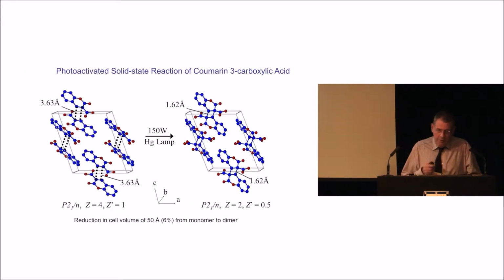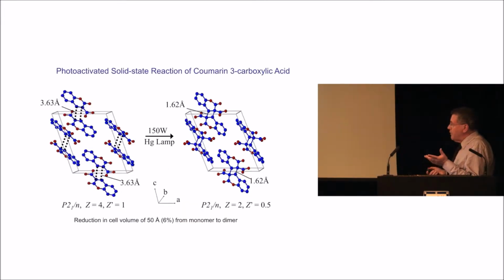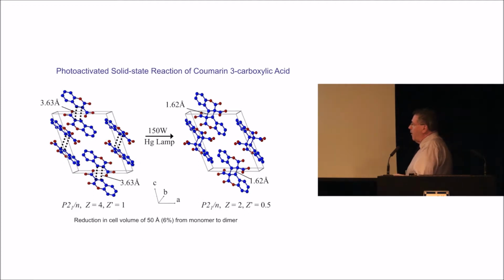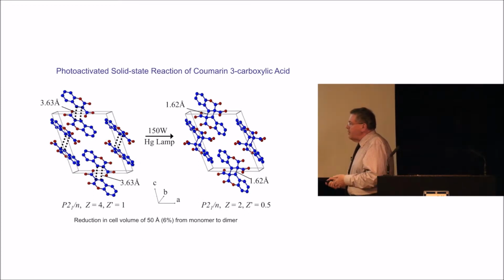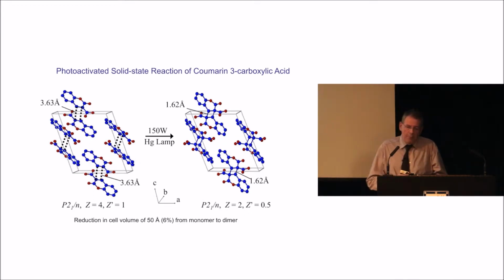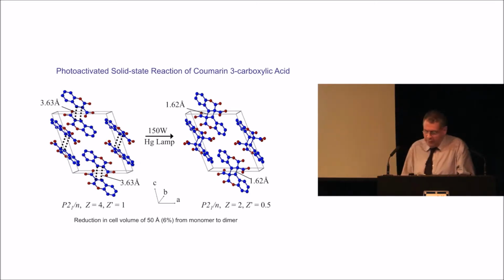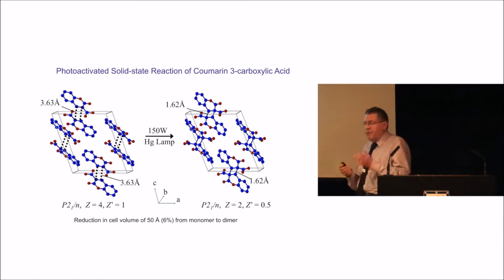And if you look at the coumarin, you can actually also do that in the single crystal. With a mercury lamp, you can see that we get a formation of the 4-membered ring there with a shortening of the carbon-carbon bond and a reduction in the cell volume of about 6%, going from the monomer to the dimer product. So fine.